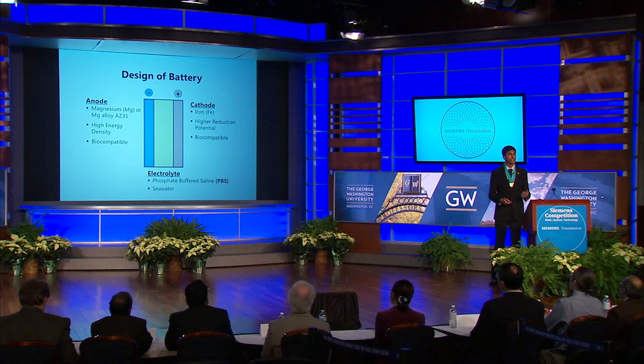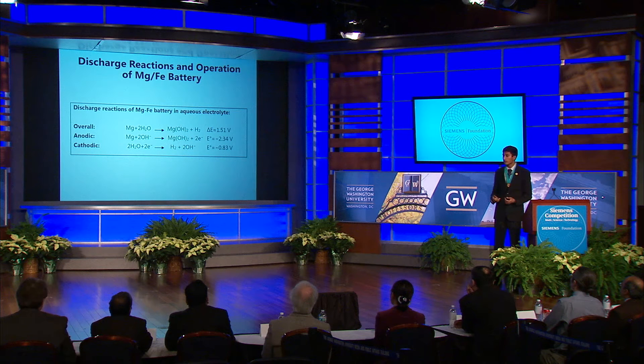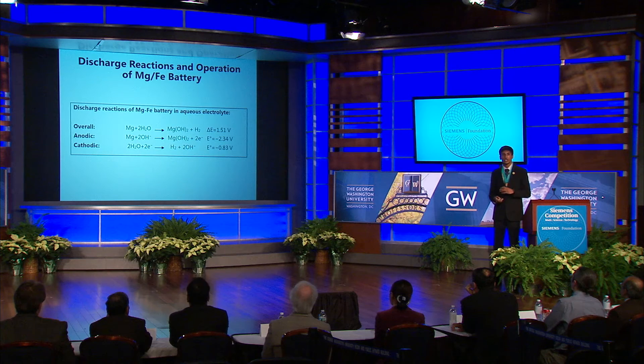The first really major decision I had to make was what materials I was going to use. I ultimately settled on magnesium and iron as my anode and cathode, respectively, because they're both biodegradable, biocompatible metals with advantageous electrochemical properties. Magnesium has a very negative reduction potential of -2.34 volts, while iron can serve as a site for water reduction, which is important because the underlying mechanism for battery operation is the cathodic protection of iron — the more noble metal — meaning that magnesium corrodes preferentially during discharge. I chose to use phosphate buffered saline, or PBS, as my electrolyte in testing because of its similarity in composition to human body fluid.